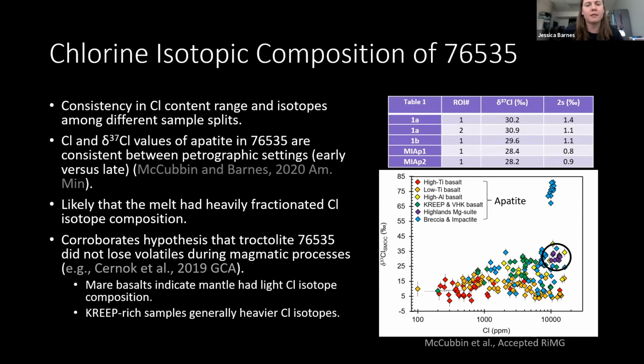And so the conclusion that we came to in the American Mineralogist paper is that it's likely that the melt, before any crystallization had occurred, the melt parental to this sample already had heavily fractionated chlorine within its melt composition. And so this really corroborated the idea, not only our urKREEP idea, but also that this troctolite, which is unshocked and very special because it's unshocked, didn't lose volatiles during any magmatic processing or crustal residence or anything like that.